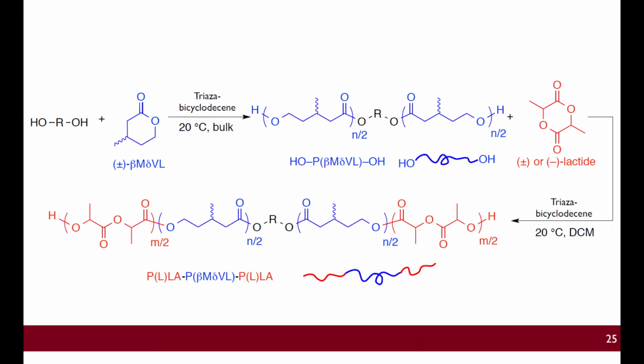That's the blue block that would go in the middle of the block polymer. It turns out to have a very low glass transition temperature, which I'll show you in a minute. But what we can do with that blue block is grow off of the ends lactide, and that lactide then can be put onto the ends in this ABA tri-block copolymer format. That's the exact type of architecture that I showed you in the Kraton materials. And in addition, we were able to do that quite efficiently.